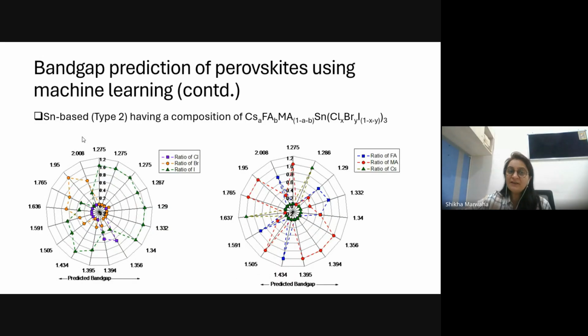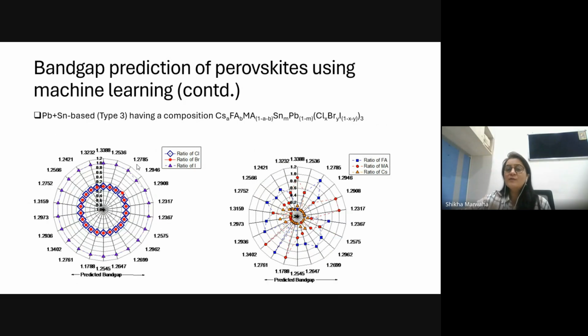Secondly, we also worked on tin based materials, where the rest of the things were the same, but only tin based materials were there. For this combination, the data set was not that large, but we were able to get a few data points out of it and make some predictions. The first again corresponds to the prediction of band gap for the perovskite based on their halides, and the second corresponds to the prediction of band gaps based on their cations. And the third was lead and tin. As I have discussed, lead increases toxicity but supports stability, and tin does the other way around.